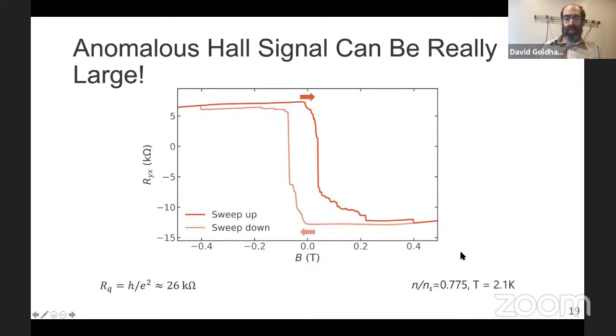Now, I mentioned that this was cooling things down. Oh, and also the size of the Hall signal has gotten bigger. It's not symmetric about 0, but if you were to symmetrize it, it's about plus or minus 10 kiloohms in size. So it's getting up toward, though not reaching, the quantum of resistance, which is what you'd expect in a quantum Hall system at high magnetic field. So this is really pretty striking and unusual. I mentioned that this was cooled down in a dilution refrigerator, but actually this measurement is made at 2 Kelvin. It turned out that this fancier cryostat was needed because we had better electrical filtering on it, because even tiny electromagnetic signals can shake up this magnet, as you'll see.